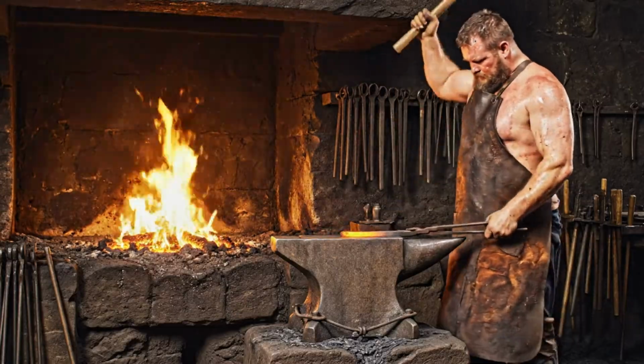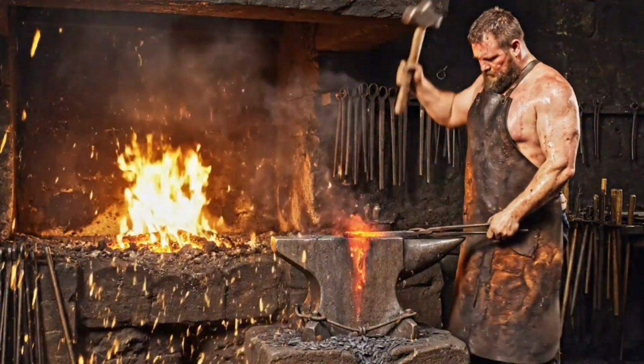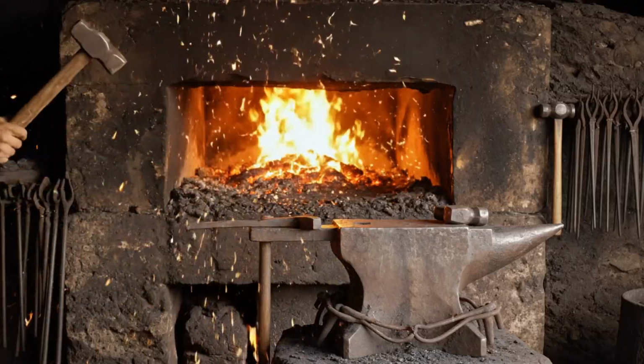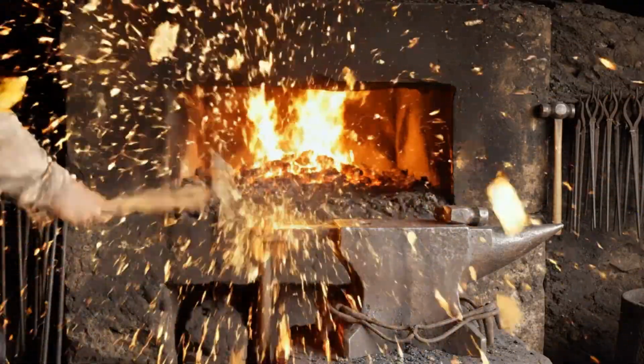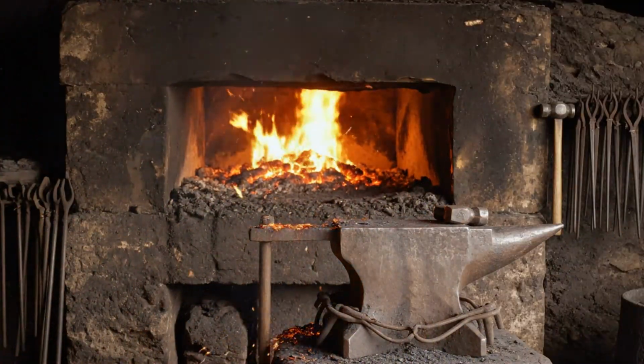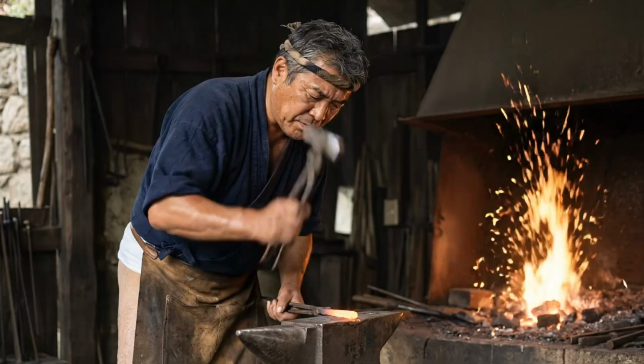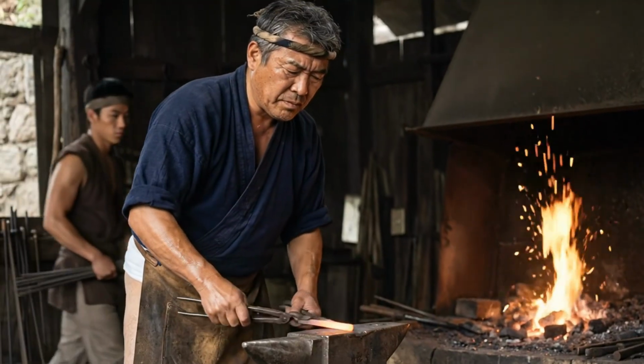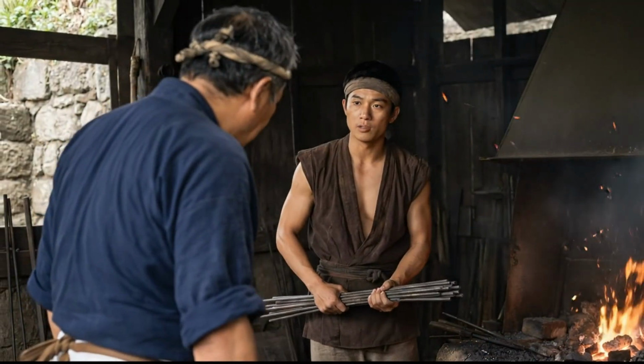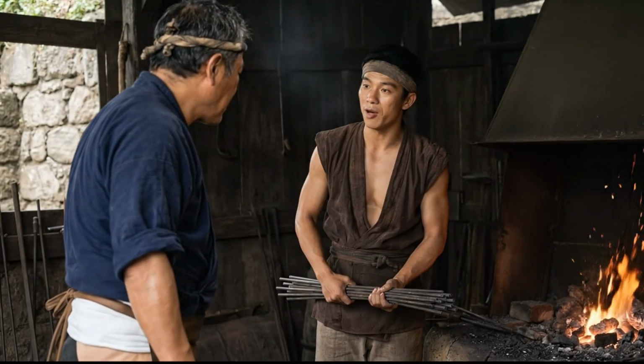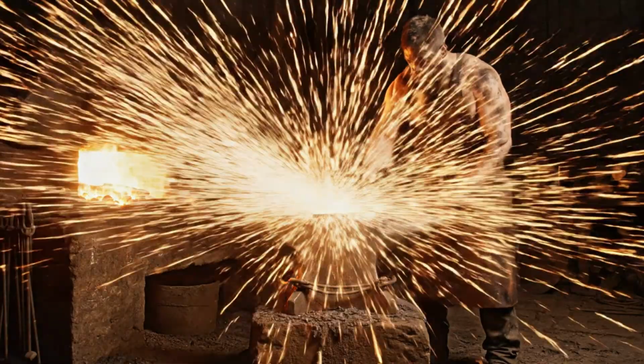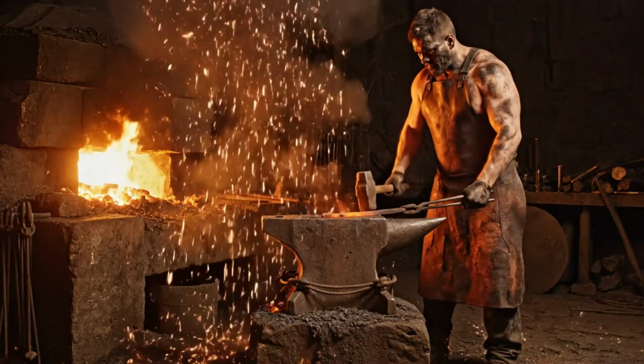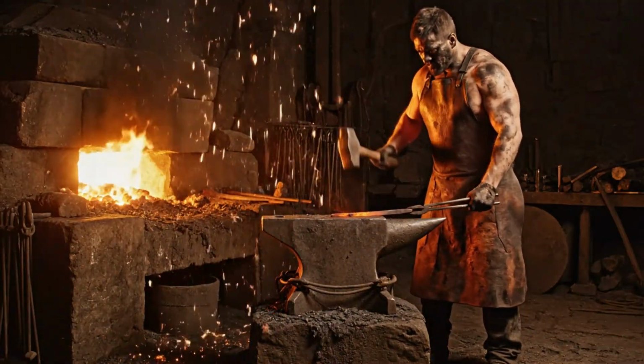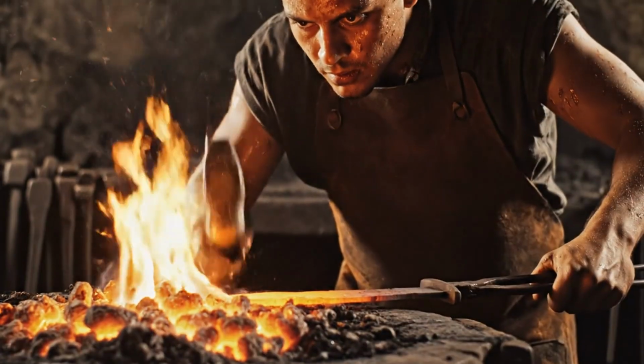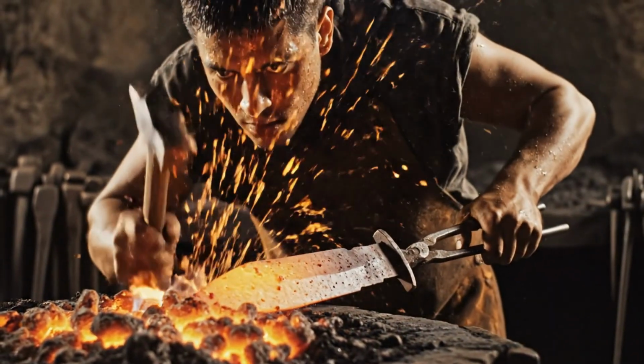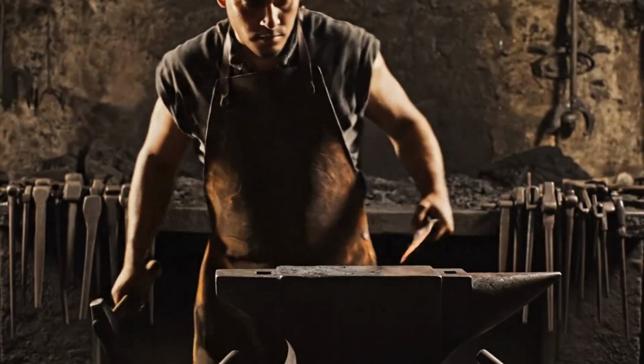The folding process that follows is not about creating layers for their own sake. It is about refining the grain structure, distributing the carbon more evenly within each chosen region, and aligning the silicate inclusions into the fibrous architecture that gives the blade its fracture resistance. The number of folds in a traditional blade is often cited in popular sources as a marker of quality, but this deserves careful qualification. Excessive folding beyond what the material requires actually begins to reduce carbon content through oxidation, weakening the steel rather than improving it. The swordsmith's skill lies in knowing when to stop, in reading the metal, rather than following a formula.